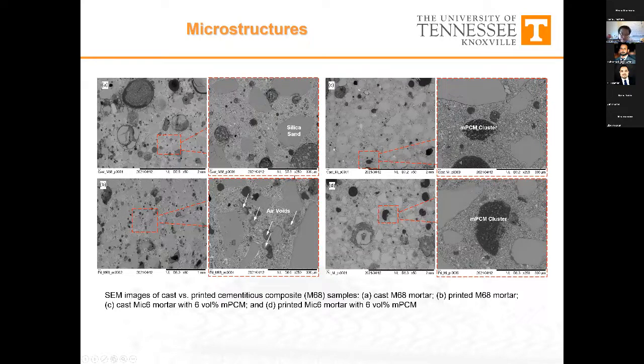Some of the interesting observations that we find here: first, for the printed sample, I think it's a consensus that we have much higher air porosity in the 3D printed mixes, which later impacts the mechanical property, which I will show in a second. But something quite interesting is that because of this lubricating effect that we talked about earlier, there are still leftover clusters, but if you watch very closely, those microcapsules are very well dispersed across the entire binder system.